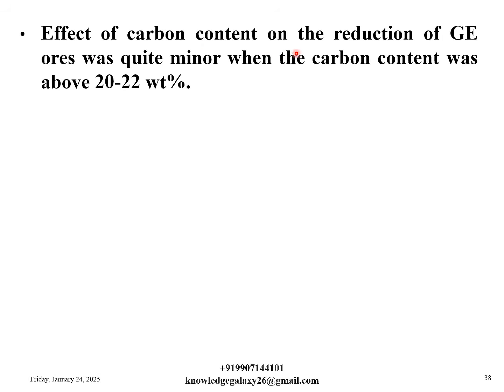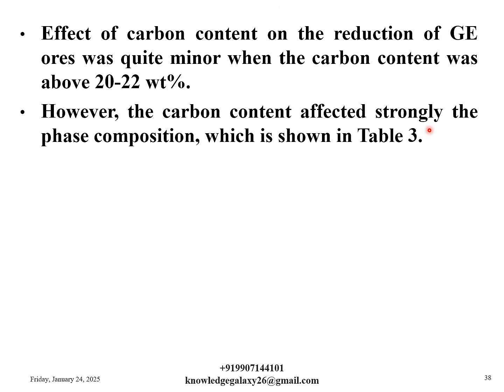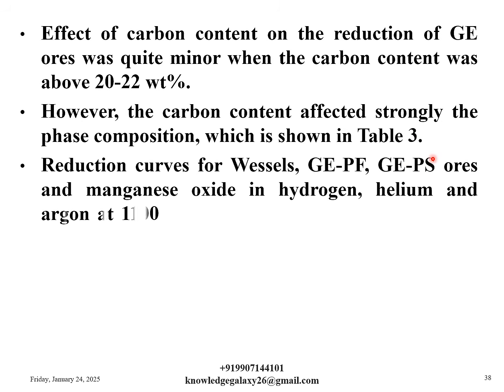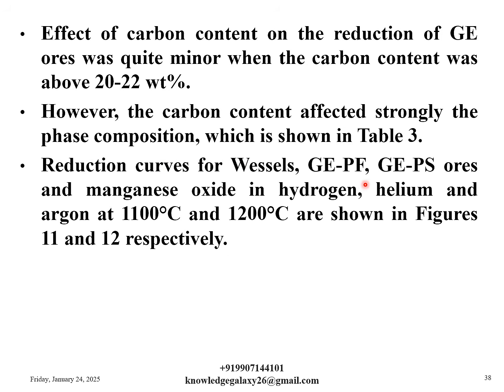Effect of carbon content on the reduction of Groote Eylandt ores was quite minor when the carbon content was above 20 to 22 weight percentage. However, the carbon content affected strongly the phase composition, which is shown in table 3 in coming slide. Reduction curves for Vessels, GEPF, GEPS ores and manganese oxide in hydrogen, helium and argon at 1100 degrees Celsius and 1200 degrees Celsius are shown in figures 11 and 12 respectively. I hope you can recall the full form of GEPF and GEPS. I have already told this in the previous slides.